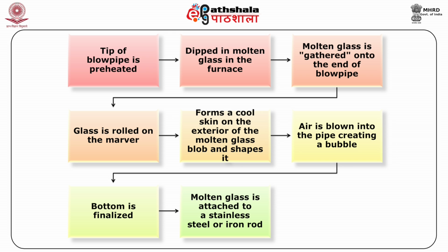This glass is then rolled on the marver, which was traditionally a flat slab of marble, but today is more commonly a fairly thick flat sheet of steel. This process, called marvering, forms a cool skin on the exterior of the molten glass blob and shapes it. Then air is blown into the pipe, creating a bubble. Next, the glass worker can gather more glass over that bubble to create a larger piece. Once a piece has been blown to its approximate final size, the bottom is finalized.